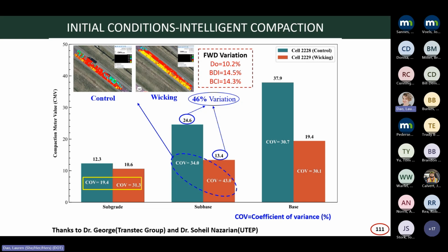So it's very important to have those initial conditions mapped, so we can understand the variation in the initial condition. Because when we are comparing between test sections, one thing is meeting the design criteria, and the other thing is that when we compare, both test sections should be orange to orange. It should not be apple to orange. So we want to compare orange to orange. But the problem is that we have nature there and we cannot control all of this. So the mapping is helping us understand the results from that perspective.